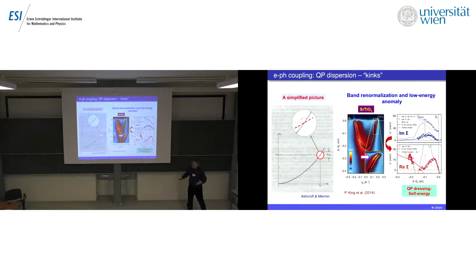Now, electron-phonon coupling, of course, influences the dispersion of the electronic states. So this is a very simplified picture where the parabolic dispersion of a free-electron, nearly free electron material is modified just near the Fermi level, the mass is enhanced, and there is therefore a kink in the dispersion. And actually, this is observed, for instance, here in strontium titanate. You can see it very well. The dispersion has a kink at an energy which corresponds to the phonon that is strongly coupled to these